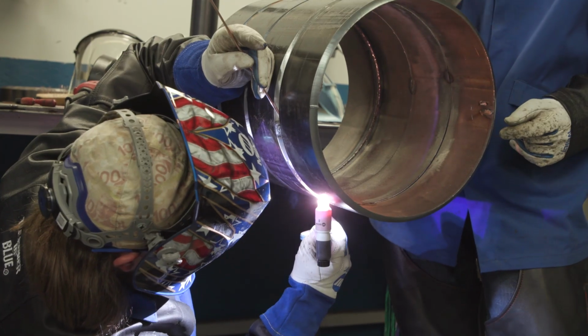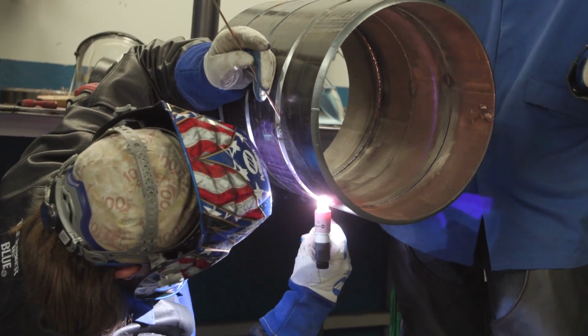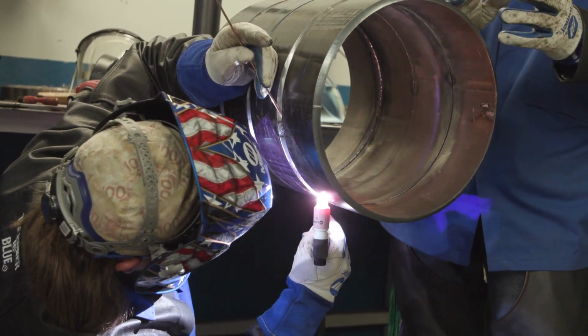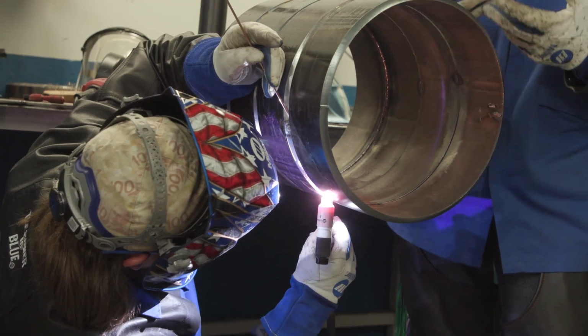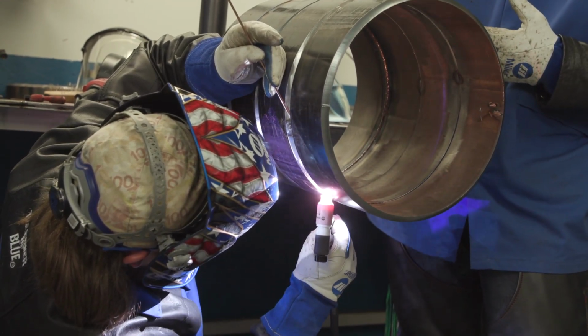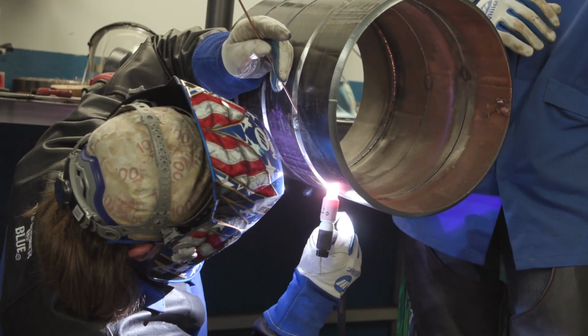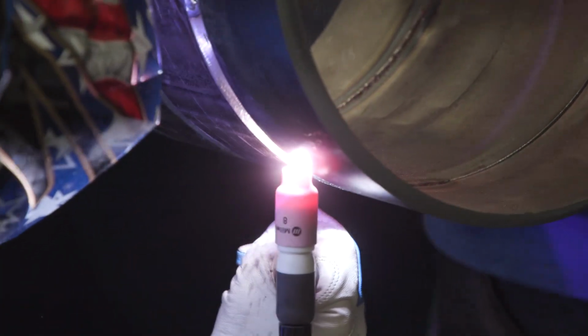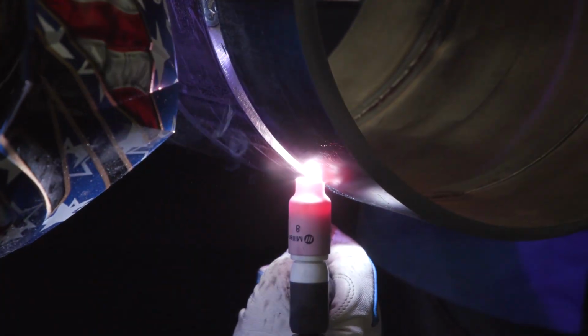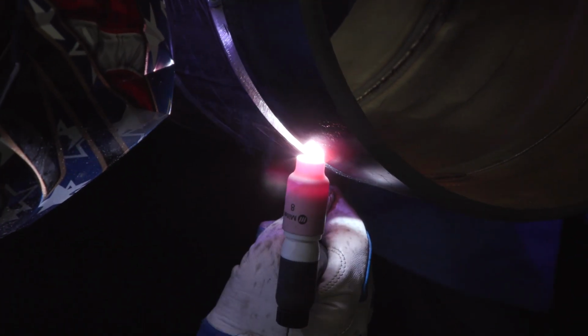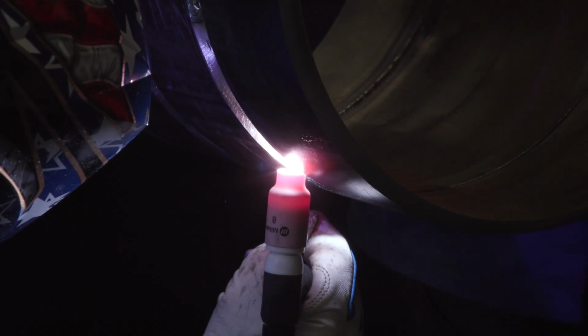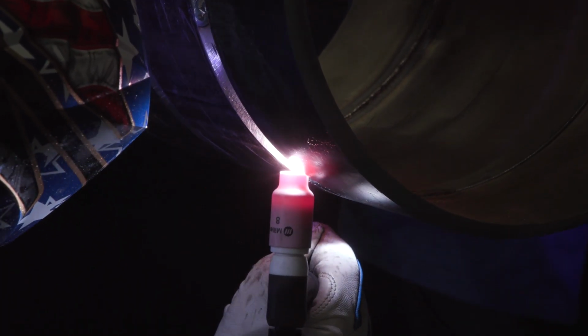Yeah, so usually, with a 36-inch and even a 24-inch, it would be very difficult to use the backfeeding, looking through the gap technique. You could do it on an 18-inch, but it's more helpful with the 5/32 because it slows down all your travel and how the puddle flows, so you actually have more control than you would over a 1/8 on this size of pipe. It's just easier to control the flow, but when it gets to something really large, it's easier to use this particular technique.